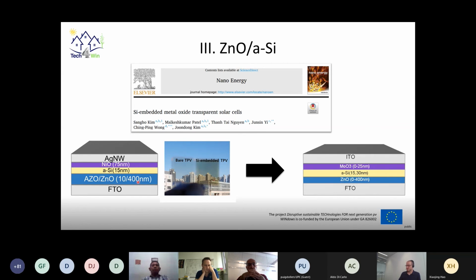So we were thinking, okay, why not giving it a try? So we put amorphous silicon between our zinc oxide electron transport layer and moly oxide hole transport layer. And then we also optimized in the first instance the thicknesses of all of it. So for the amorphous silicon, we had a look at 15 and 30 nanometer, as you will see on the next slide. For the moly oxide, we optimized up to 25 nanometers, and for the zinc oxide, up to 400 nanometers.